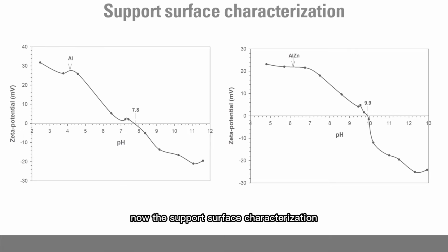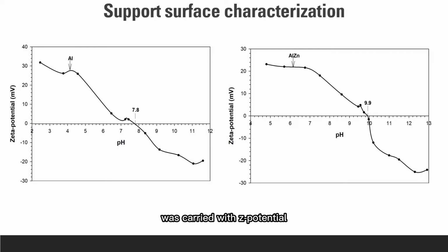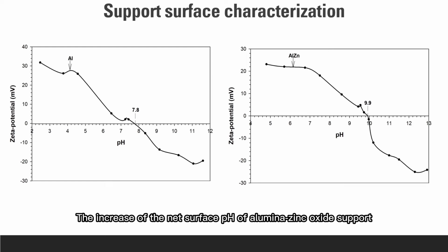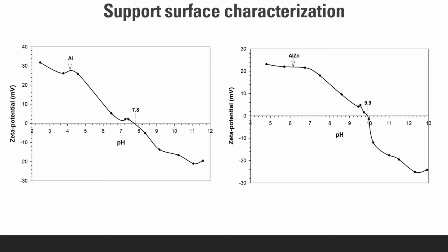Now, the support surface characterization was carried out with zeta potential to determine their net surface pH. The sol-gel alumina support showed a net surface pH of 7.8, whereas alumina zinc oxide exhibited a net surface pH of 9.9. The increase of the net surface pH of the alumina zinc oxide support is associated with the isoelectric point of zinc oxide.